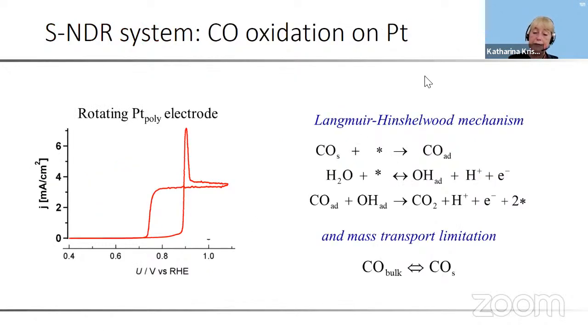Okay. The by far most prominent S-NDR system is the oxidation of carbon monoxide on platinum. Here you see a cyclic voltammogram with a beautiful bistable region, and this was obtained in a concentrated sulfuric acid electrolyte. And this system oscillates due to the Langmuir-Hinshelwood mechanism, due to the electrode kinetics.